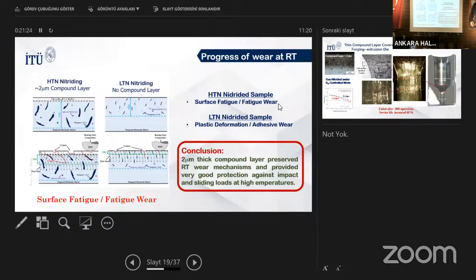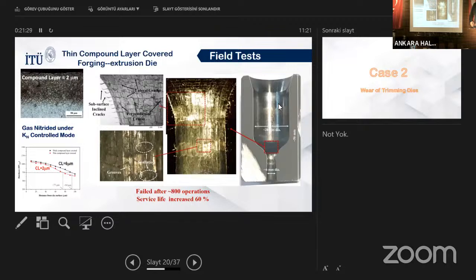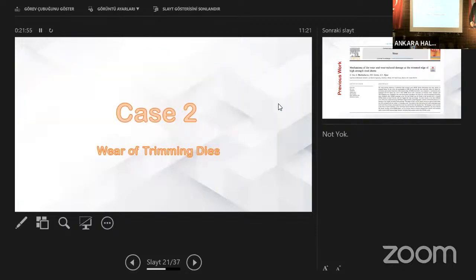This is the model that we have proposed. Then we applied the process parameters that we determined to the real forging extrusion line, and they worked for 800. So about a 60% increase in the service life after being covered with a thin compound layer. So this is the first case. The second case, do we have time?